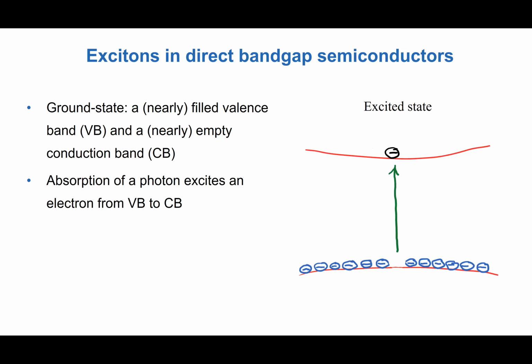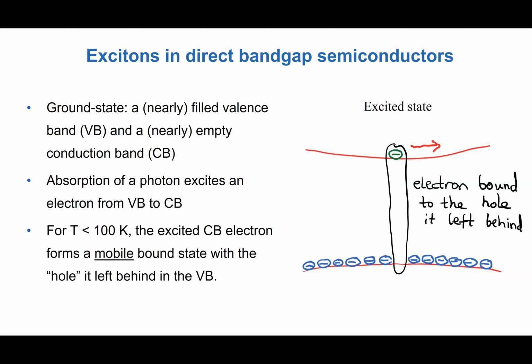When we make an optical excitation, we take one of these electrons and put it into the conduction band. And what happens now? If this electron were to wander off away from the hole that it left behind, then it will be subject to the strong Coulomb interactions with the electrons at those sites in the semiconductor. Whereas if it sticks around and binds to the hole that is left behind, then its energy would be smaller. That's the idea of what an exciton is: in the presence of strong interactions, the electron can lower its energy by correlating its motion with the hole that it has left behind in the valence band.